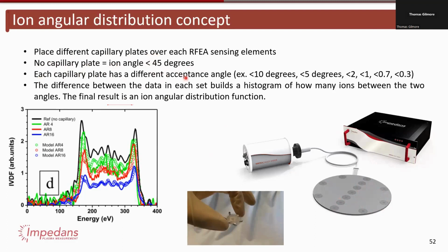And then if you apply different capillary plates with different angles, you basically can build up a histogram. So what you do is you have all these different angular plates all around at once. And by subtracting, you get the 45-degree bucket. If you subtract the 10 degrees, that tells you what's between 45 and 10 and what's 10 and below. And then if you subtract the 5, that's going to split from 10 to 5 and 5 and below. And you get the idea.